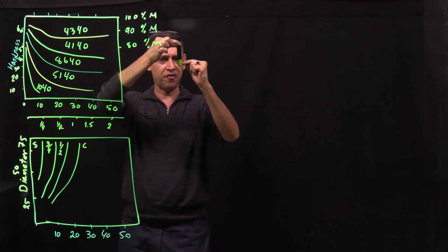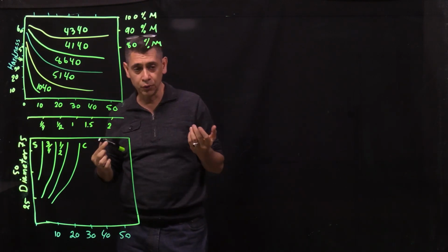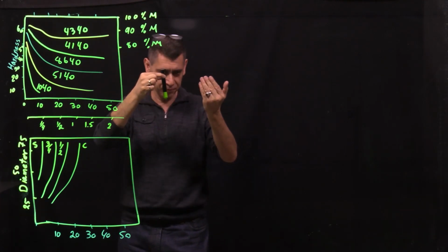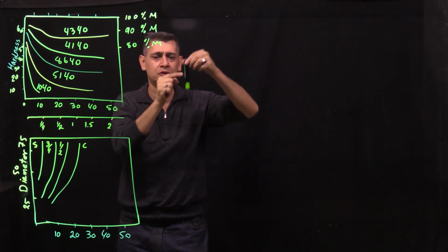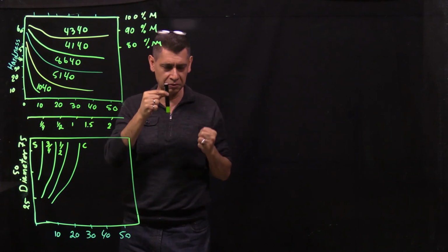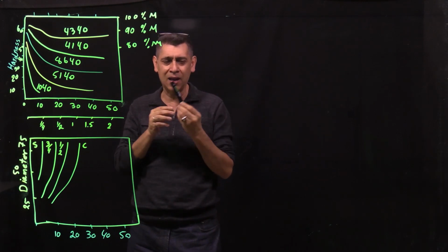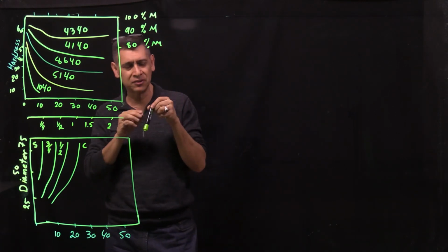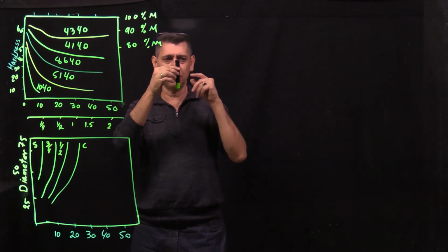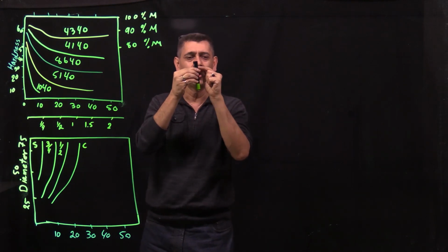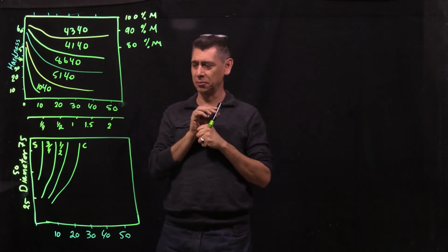And obviously, the further you are from the cooling head, where water is splashing, the cooling rate is lower. So that's the meaning of conversion of the distance to a cooling rate. These are completely related. And we mentioned that it is using ferrous alloy, and regardless of the alloying elements, they have relatively the same thermal conductivity. That's why we don't need to worry about what alloy this is when we go to the actual cooling rate with respect to the cross section. We will talk about that in a bit.